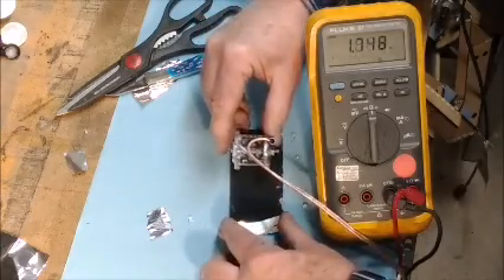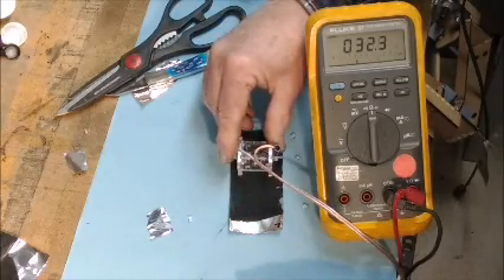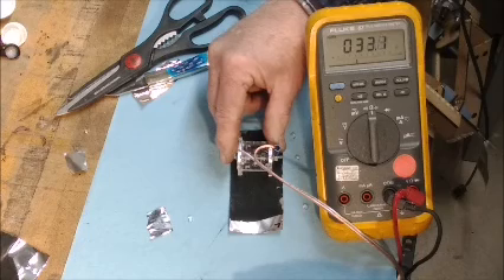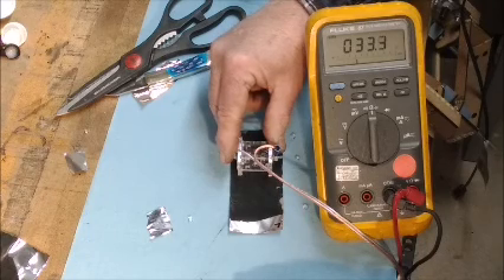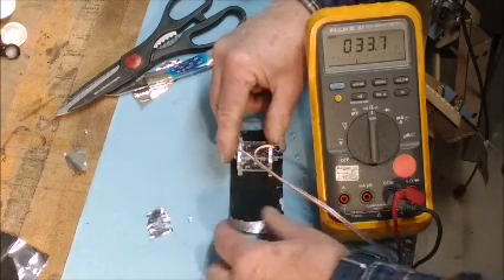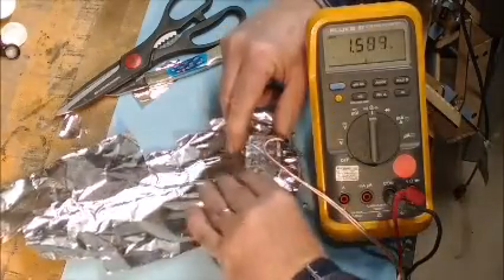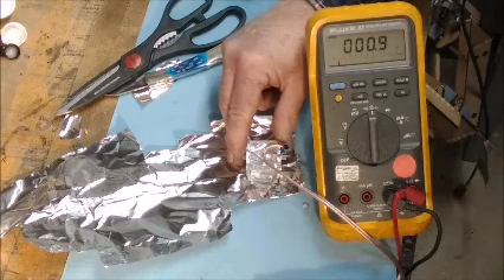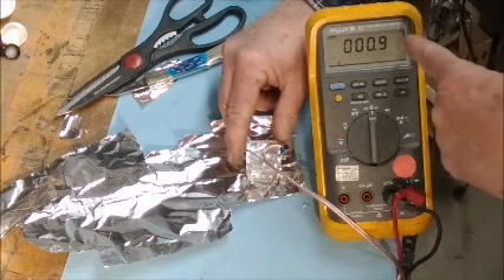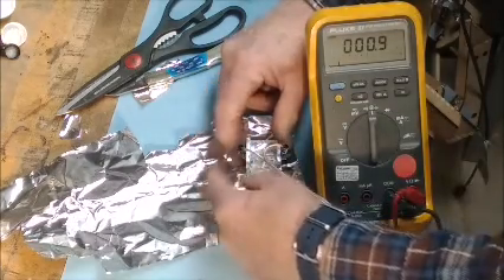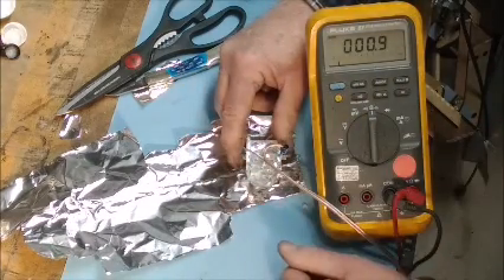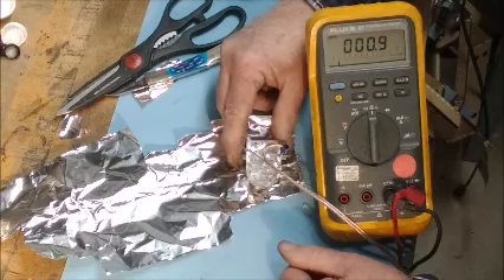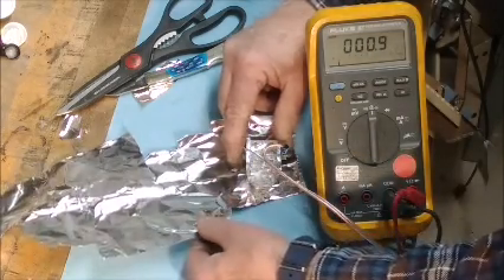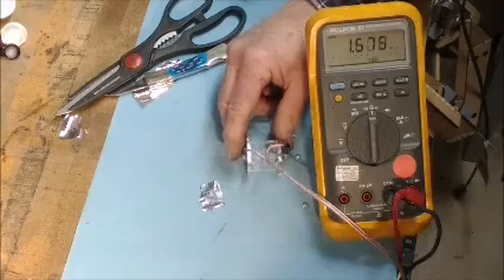So we started out with this piece here. My not very good conductive carbons are about 33 ohms per square. Obviously the tinfoil itself is going to show me what the contact resistance is of the complete circuit. So here you've got the resistance of the foil, the contacts here, the actual meter connection. So from whatever reading we take, we can subtract 0.9 ohms per square.